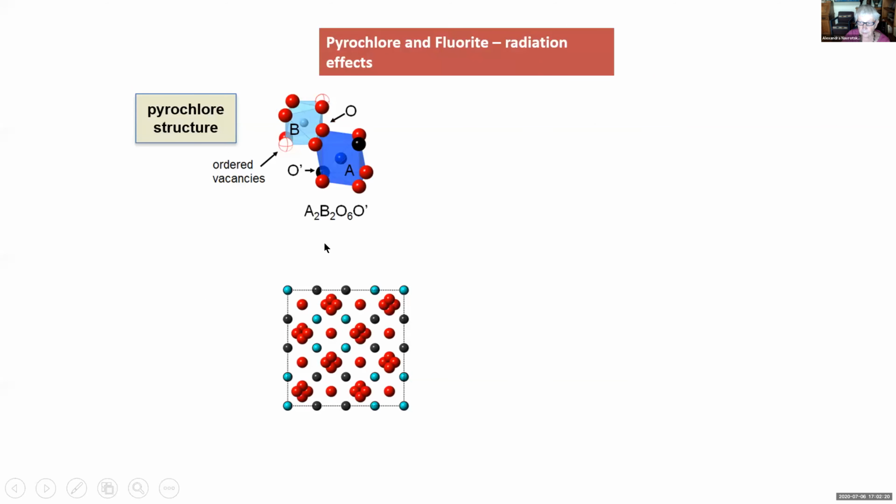So let's talk about the structures. The reason for forming these derivatives of the fluorite aristotype is to get better local coordination for different size cations and to accommodate the oxygen vacancies. So the questions that one has, first of all, are the positions of the oxygen vacancies and the positions of the cations random, or are they correlated? Secondly, how much order of the cations is there? And if there's a lot of order, then the cation sites become distinct. The ideal pyrochlore structure is a defect structure.